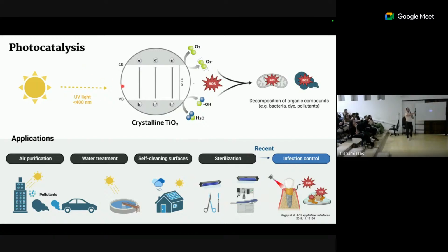If you see the structure of this molecule, we have the valence band and the conduction band. When we expose this molecule to UV light, for example, we're going to have a flow of electrons from the valence band to the conduction band, and then at the end we have the formation of reactive oxygen species. The distance between the valence band and the conduction band might be 3.2 electron volts, so it works with UV light. If you want an effect with visible light, we need to reduce this band gap.